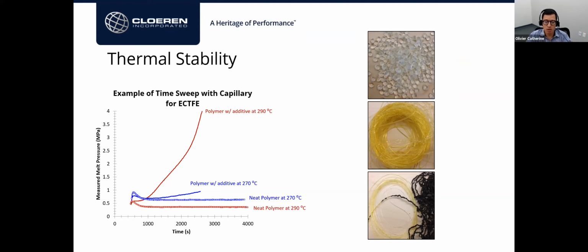which I prefer is always to go back to their process and see what created the issue of melt temperature that is too high. And that's a very common problem in extrusion, is that the viscous heating or shear heating is usually much higher than people think. And then people try to correct that by having lower set points in the melt pipes and feed block in the die, and that really creates non-isothermal extrusion at this point, which is very difficult to balance. So it's always good to go back to the source and fix the issue of the too high shear heating.